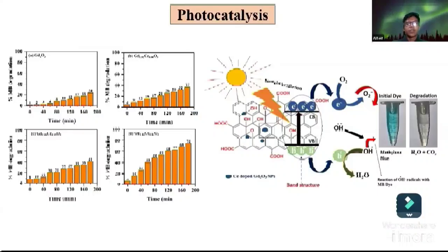The excited electrons react with oxygen to form superoxide radicals, while the holes react with water to produce hydroxyl radicals. These radicals are highly reactive and they attack the methylene blue dye molecules that we tested and break them down into simple harmless products like CO2 and H2O. As shown in the graphs, undoped gadolinium oxide shows lower degradation, whereas cerium-doped gadolinium oxide achieves up to 74% degradation under sunlight, proving its enhanced photocatalytic performance.